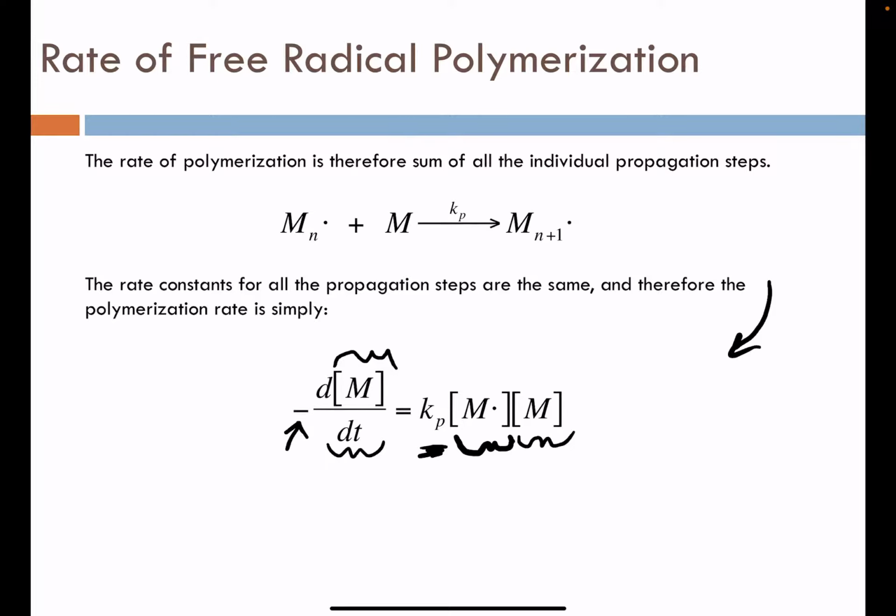So clearly, if we want to have a faster polymerization, we would want to have more initiator to generate more radicals. This would emphasize that middle term, give us a higher concentration of radicals and ultimately a faster rate. Or we could go to very high concentration monomer, perhaps even eliminating solvent altogether to give us faster polymerization, and ultimately we can see the implications there. Again, Kp is mostly set by the monomer selection, and we're not going to see very much impact by going to different conditions. We can't really do much there.